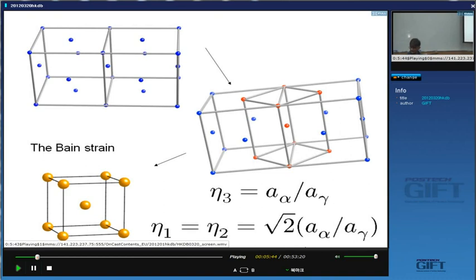So it's a homogeneous deformation which would change the austenite into ferrite, or if I leave some tetragonality, it could also be a body-centered tetragonal cell of martensite. And the deformations required are written here. So this is just a ratio. Along the z-axis, we just have the ratio of the lattice parameters of ferrite and austenite. And along this axis, you can see that we are deforming the 110 direction of the austenite into the 100 direction of ferrite.